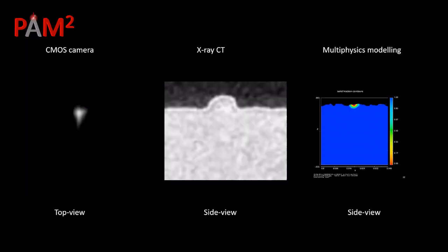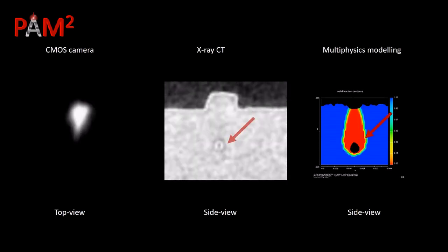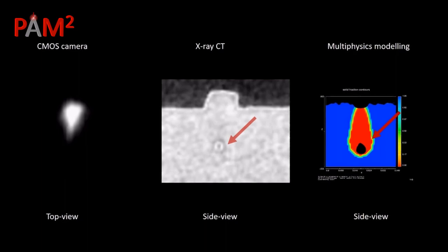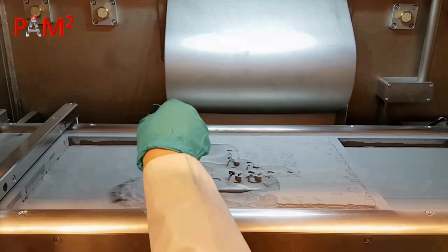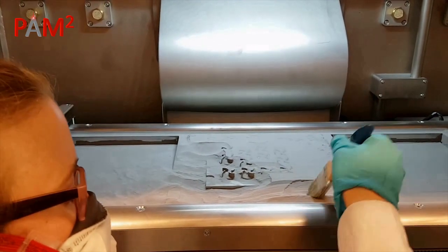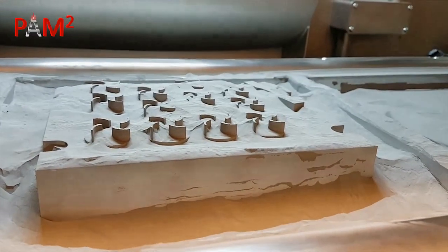Depending on the local heat transfer conditions, the behavior of melting changes from insufficient melting to optimum melting to overheating mode. Both insufficient melting mode and overheating mode lead to porosity, which reduces the mechanical properties of the parts. To minimize or avoid this problem, a better understanding of the relationship between the effect of process parameters and final part